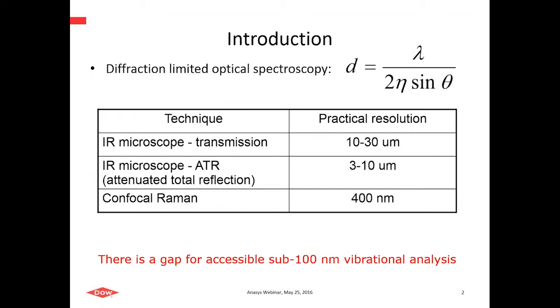As with any optical technique, infrared spectroscopy is spatially limited due to diffraction, and that's shown at the top by the Abbe criterion for spatial resolution in a diffraction-limited optical system. Theoretically, this limit depends both on the wavelength in the numerator and the numerical aperture related to the refractive index of the optics. So for this region in the mid-IR, spatial resolution is going to be limited, and it will be variable. This table attempts to give you an appreciation for that.